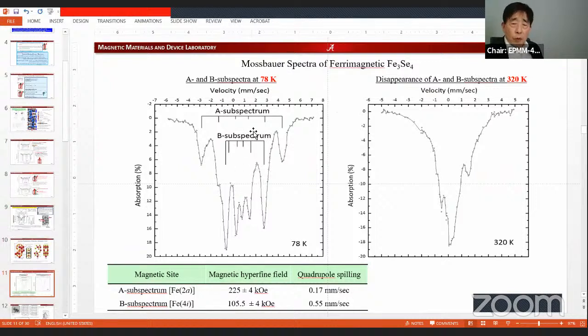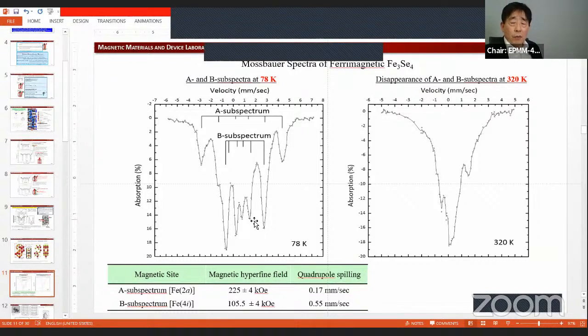This is the Mössbauer spectrum for iron selenide. This is at liquid nitrogen temperature here. Once we increase the sample temperature from 78 to 320 K, this multi-peak becomes very few peaks, and it looks like a single peak. That 320 K is called the Néel temperature, otherwise the Curie temperature, right here. This is the room temperature.